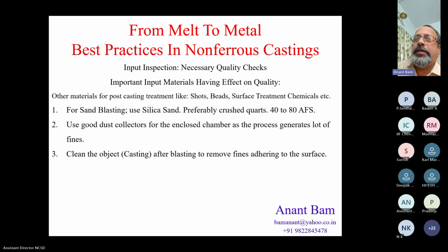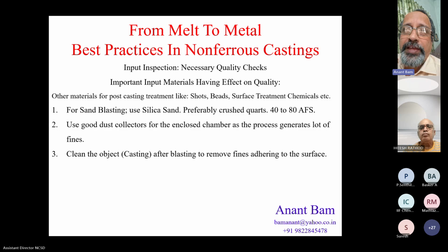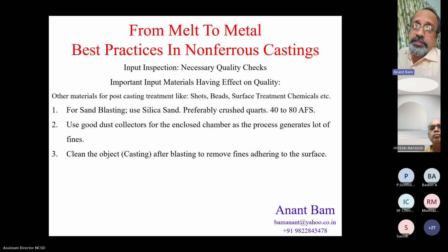Now we come to sandblasting. Sandblasting is a different process. It needs to have an enclosure with a dust collector and all those things. Although the shot blasting machine also has a dust collector, the creation of fines is very little in shot blasting, but the dust creation in sand blasting is very high. And hence, the dust removal or dust extraction is the most critical phase in sand blasting.